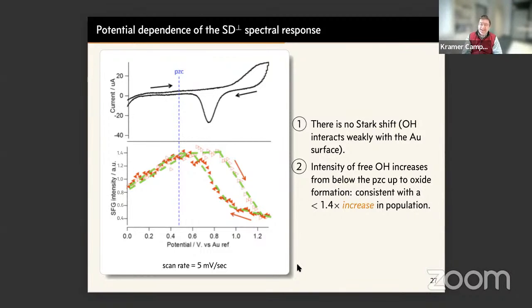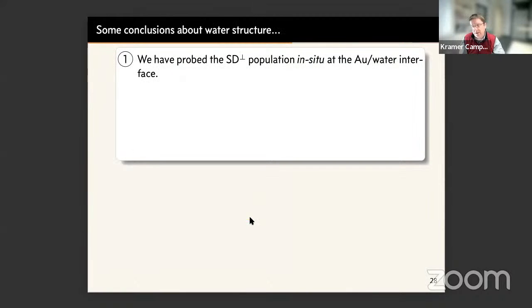Curiously, you also see that the intensity of this feature, plotted at the bottom as the integrated intensity, increases from below the potential of zero charge up to oxide formation. It's pretty flat up to where you start to see the oxide, disappears as the surface is oxidized, and only reappears as the oxide is reduced. But there is no hysteresis. The system is very reproducible, and you can do this experiment as many times as you want and see the same kinds of features.